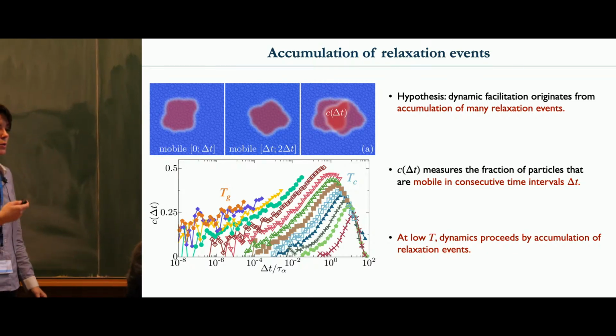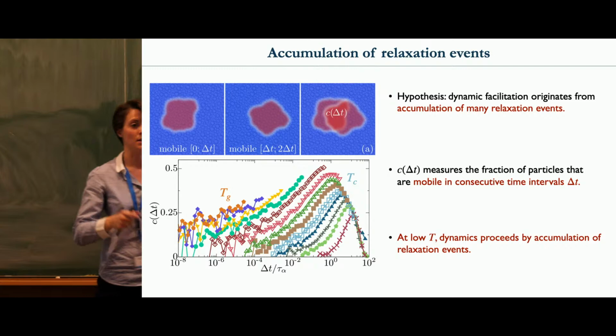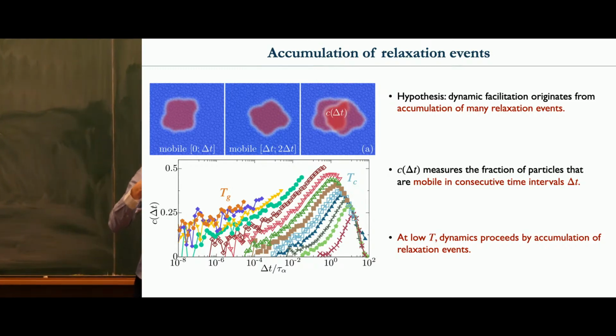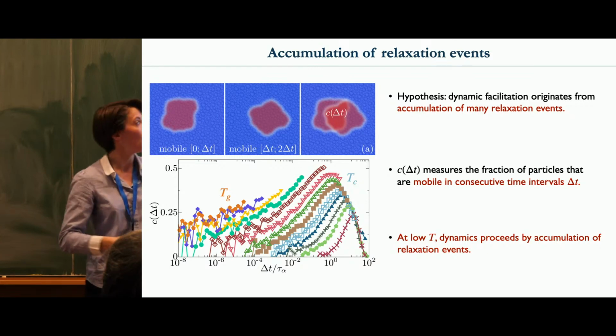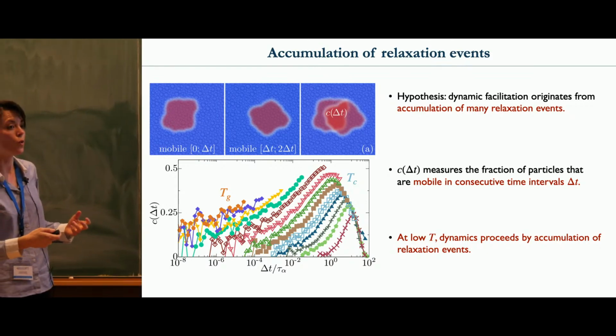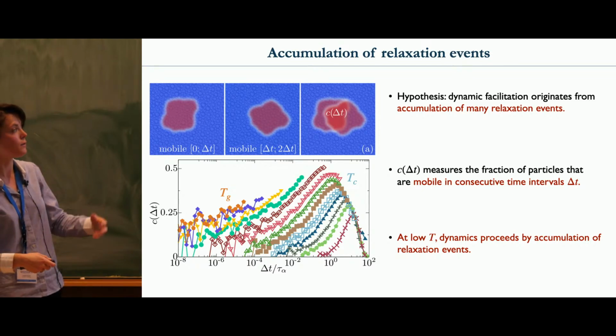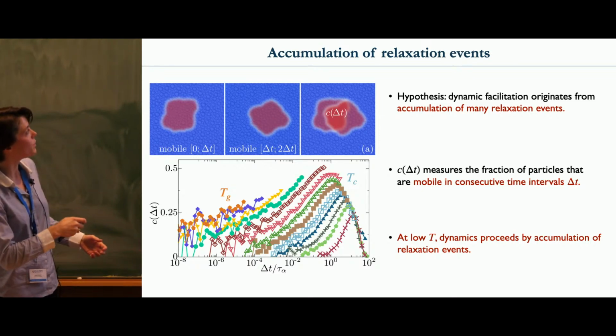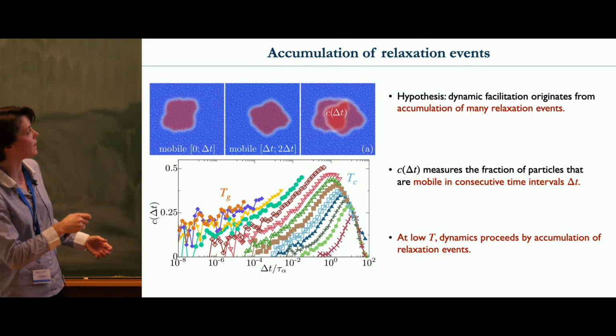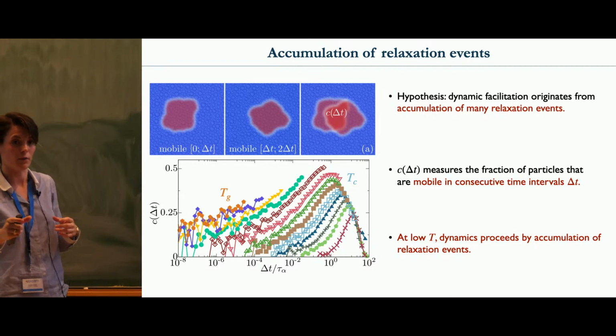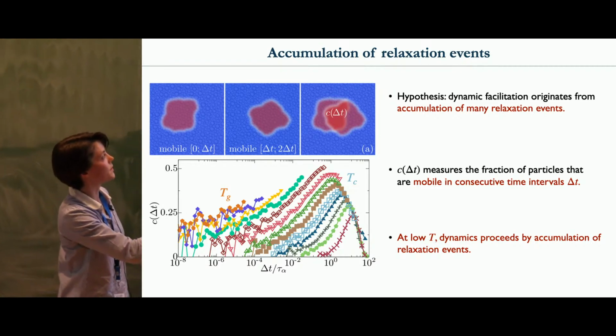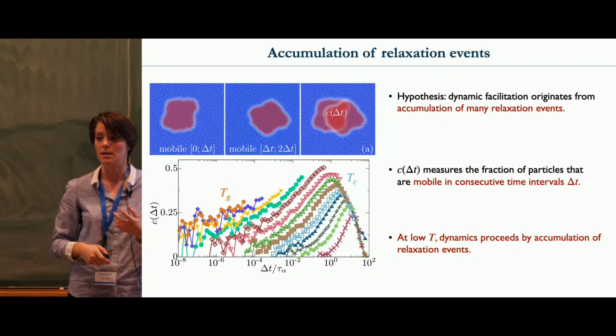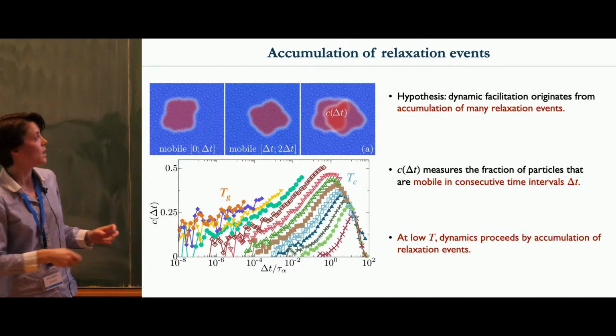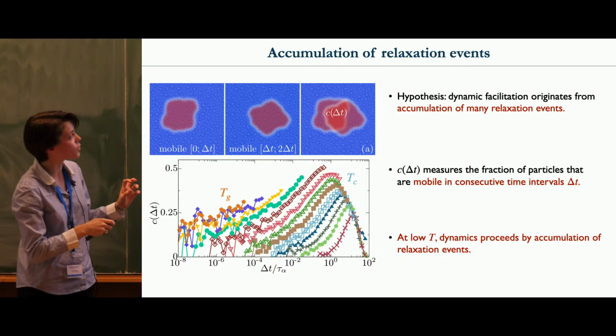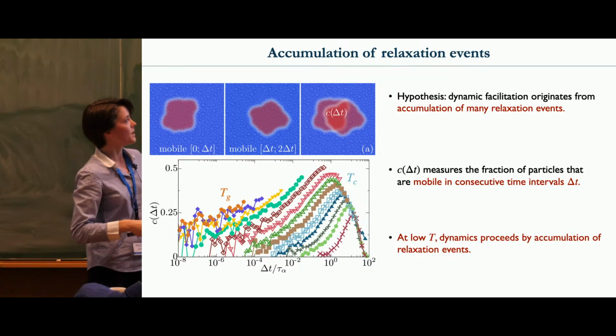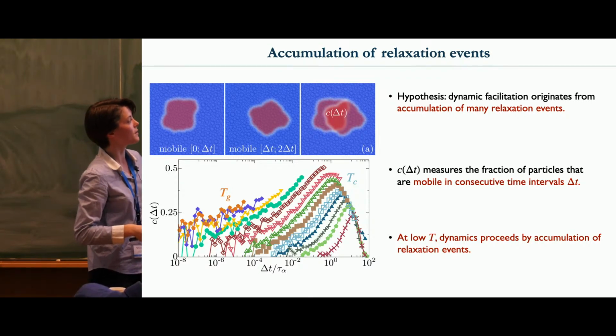Now in the simulations, what I tried to give you a flavor of is that in these mobile regions, you have an accumulation of many, many relaxation events. So we introduced a new way to quantify this idea that the dynamics repeats itself and accumulates at one location. Here we look at the particles that are mobile between 0 and delta t, and then we look at the next time interval, and we look at the fraction of particles that are mobile in the two regions. This indicates how much the dynamics accumulates in one region as a function of this time interval. This is a measure of how repeatable or accumulative the dynamics is.